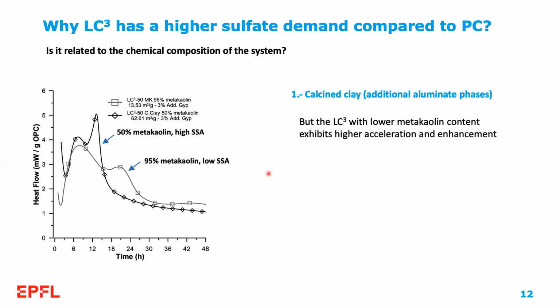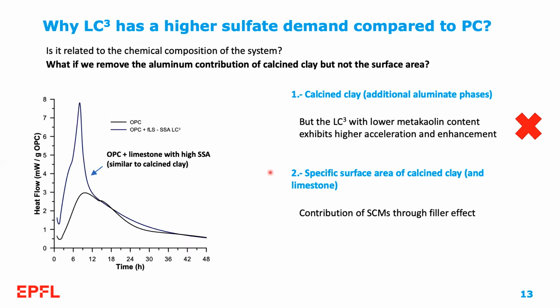And in order to confirm that, we replaced calcined clay by a material that doesn't contain any additional alumina, in this case, a very fine limestone powder, but it offers the same surface area contribution as calcined clay. And we observe the same type of enhancement of the aluminate reaction as we see on LC3 on a system, in this case, that actually has less alumina than the control PC that we have down here.